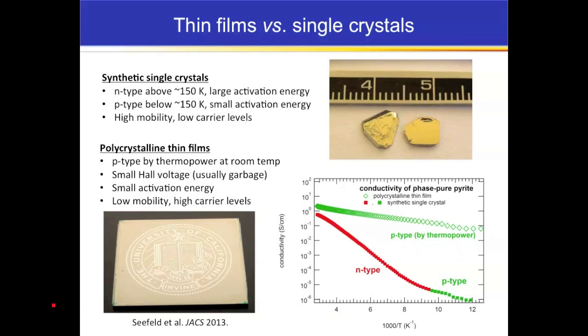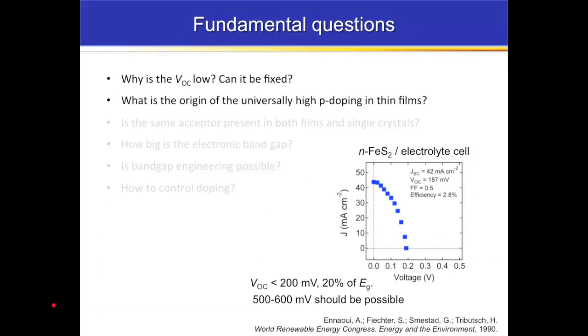What the polycrystalline thin films look like are all, regardless of how we make them, they all look something like this. They are P-type. We have to measure the P-typeness by thermopower because the Hall voltage is too small to get a carrier type out of. They have very small activation energies compared to the single crystals, and they have the opposite of the single crystals. They have low mobility and high carrier levels as opposed to high mobility and low carrier levels. And so by comparing these 2 sets of behavior, we found that we can learn a lot about what's wrong with pyrite. Okay?